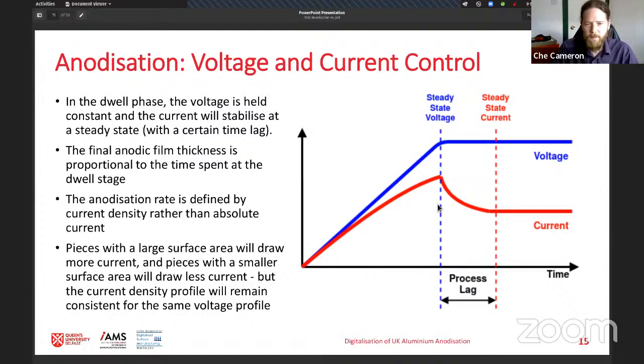And then during this time, there's a balance between how quickly the oxide is being dissolved and how quickly it is growing from the metal. And obviously it's growing faster than it's being dissolved if the process is running correctly. So the longer you spend in this dwell phase, that makes for a thicker coating, and that's how you control the thickness of the final oxide coating.